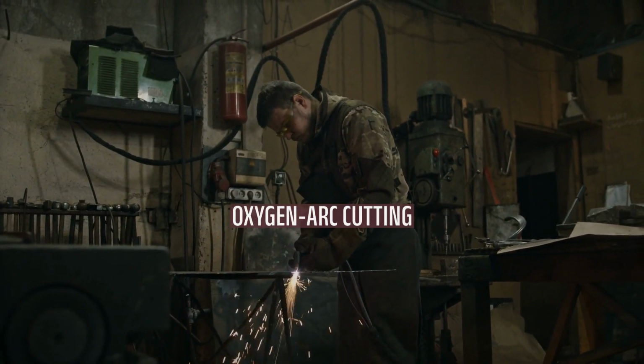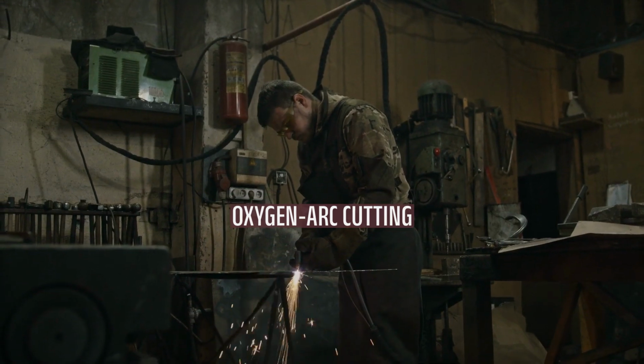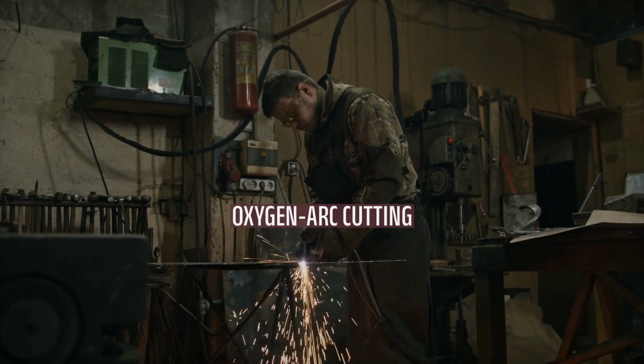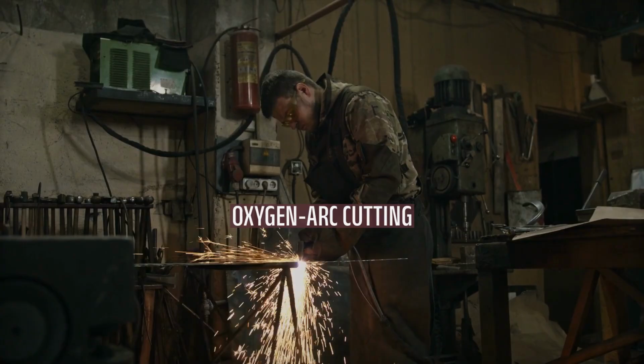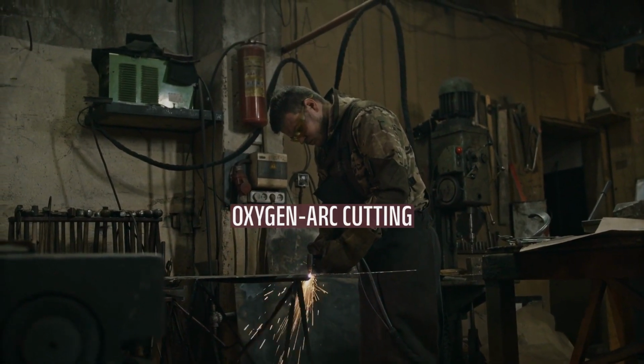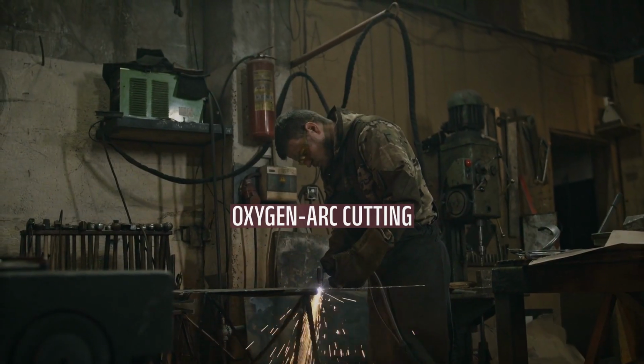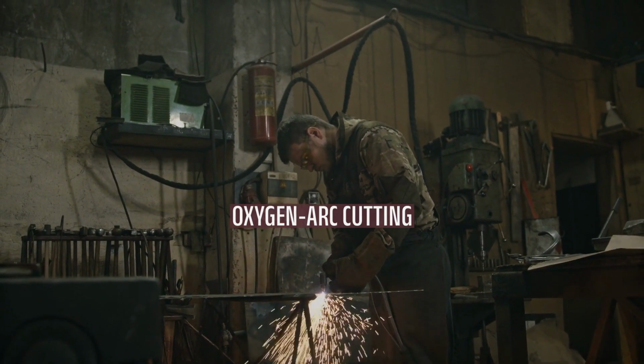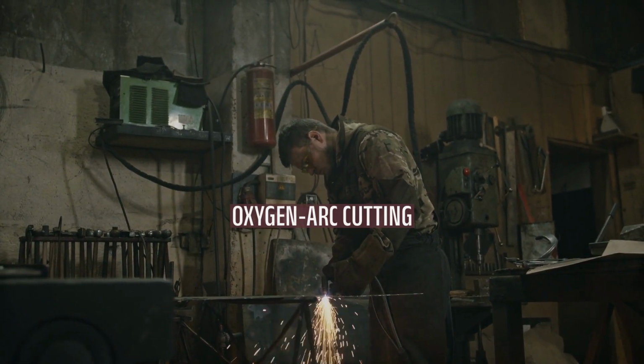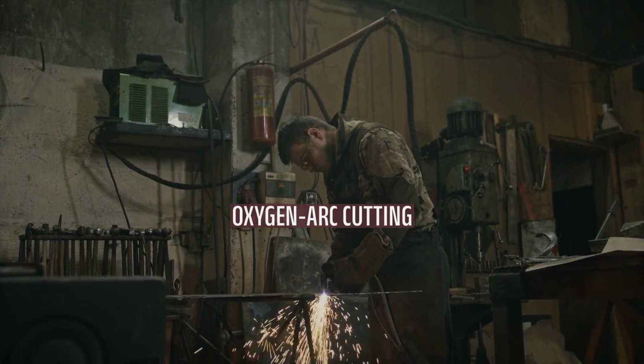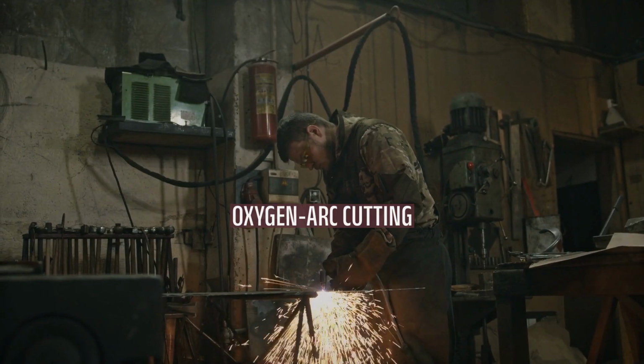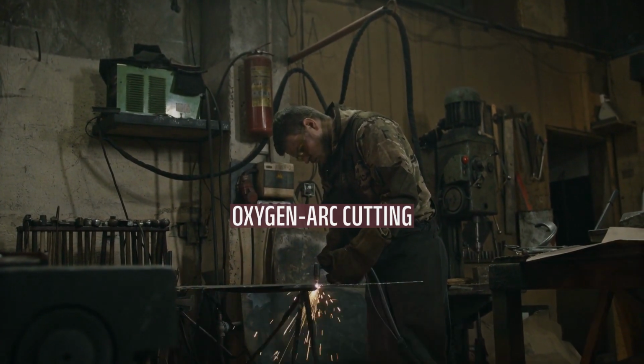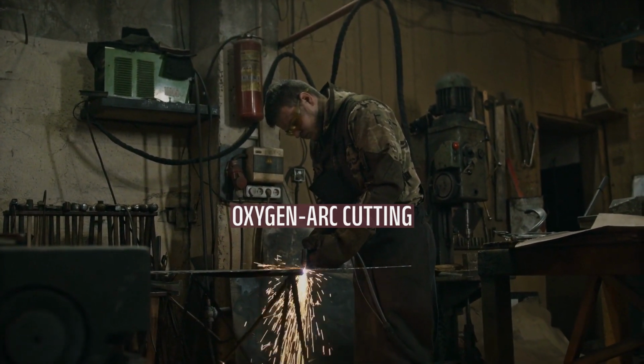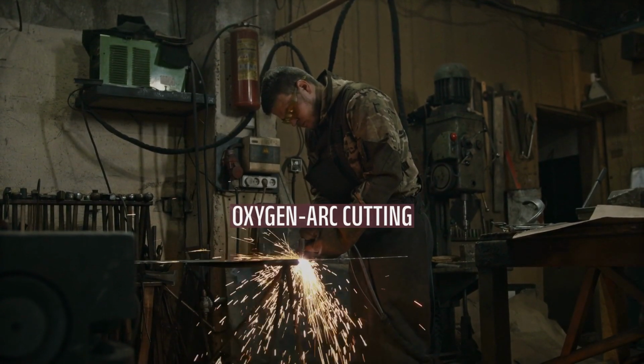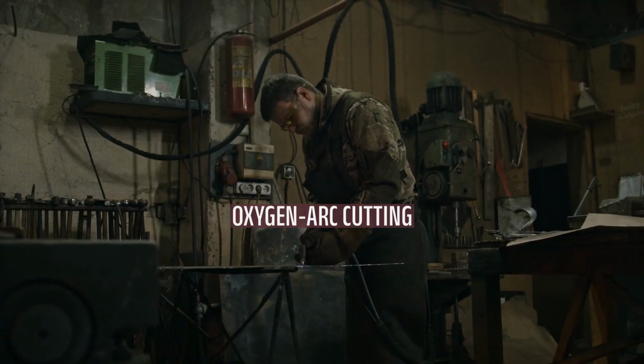The flux is also an electrical insulator, which protects the diver in case of accidentally touching the electrode, and it prevents side arcing in tight spaces. Exothermic electrodes will continue to burn once ignited as long as the oxygen flows, so the diver may have the current switched off after starting the cut, although the system will cut metals faster if the power remains on as the arc produces additional heat.